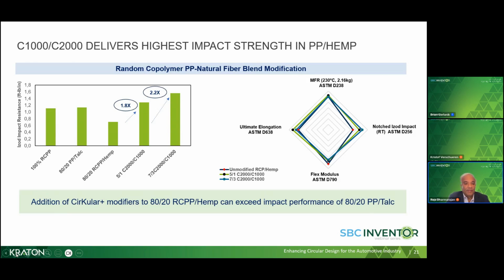So in order to improve the notched Izod, we add our C2000 and C1000 grades at a ratio of 5% and 1%. And you can see that the notched Izod goes up by a factor of 1.8, which matches up with the performance of the PP talc compound. Now, if you further increase the modifier content to 7% and 3%, we see that the notched Izod goes up by a factor of 2.2. In all of these cases, we are also able to maintain the processability.